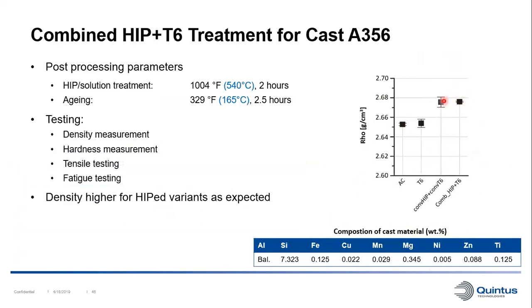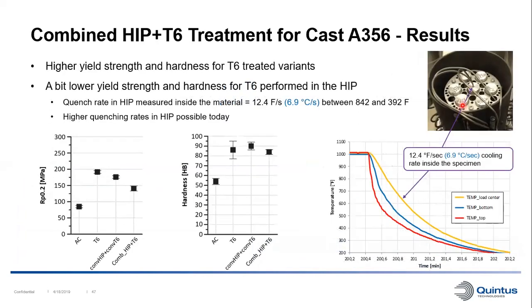And as expected, the two HIP variants have a higher density than the two that are not HIP'd. Here we see the results in terms of yield strength and hardness. And the conclusion from this slide is that the strength and hardness is higher for the heat-treated variants compared to the as-cast variant, as expected. And we can also see a little bit lower strength with the combined HIP and heat treatment variant compared to the conventional heat-treated variant.